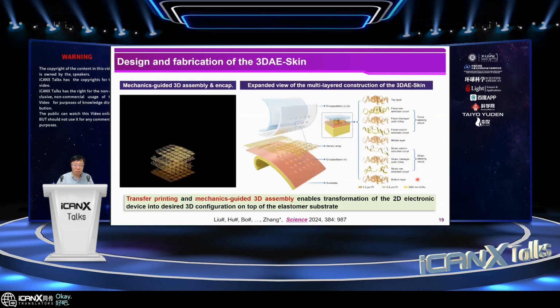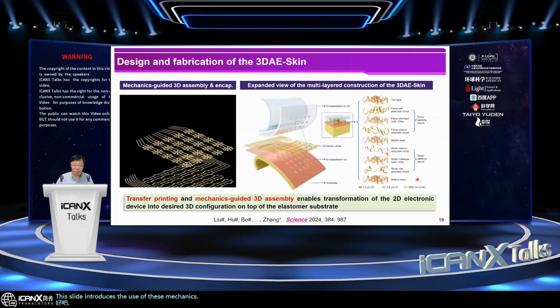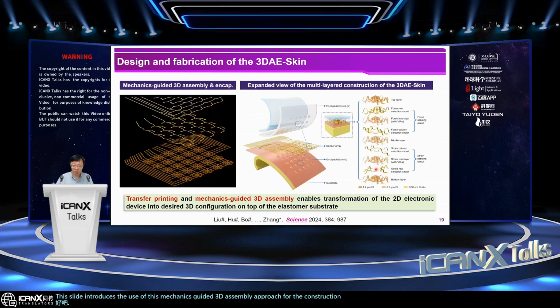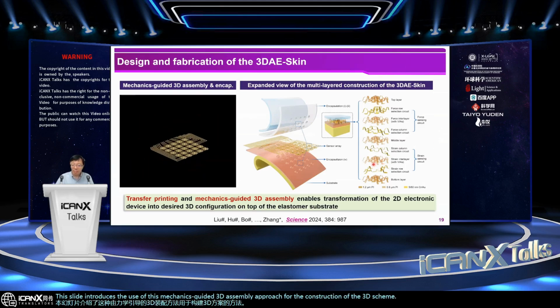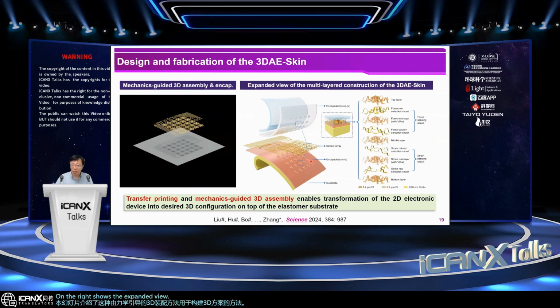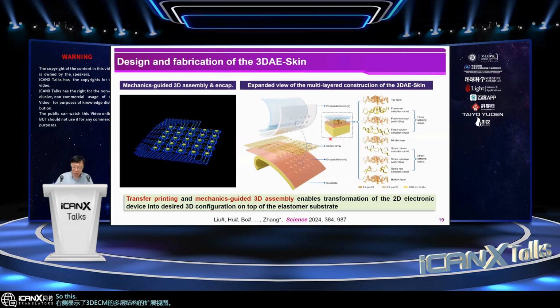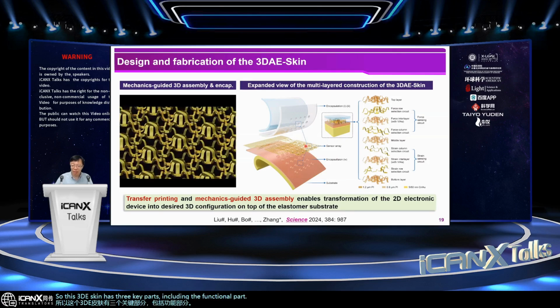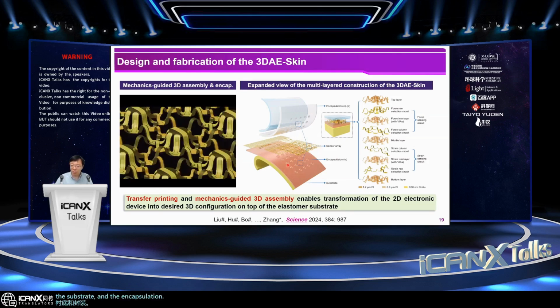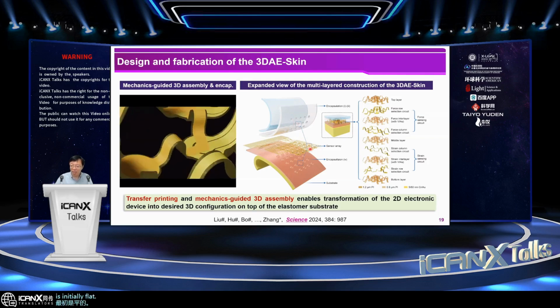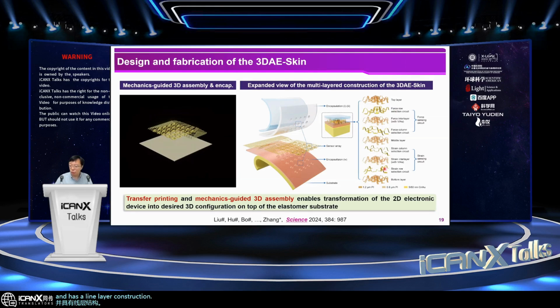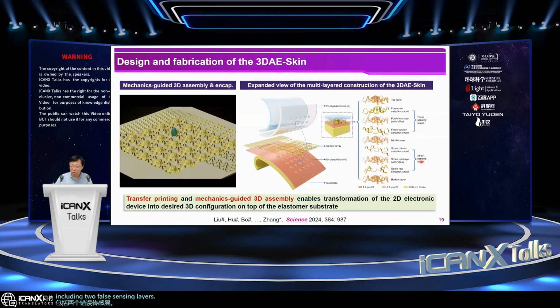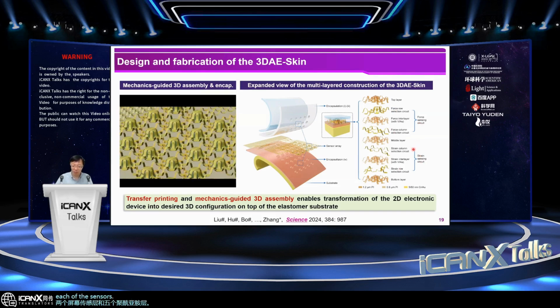Okay, this slide introduces the use of this mechanics guided 3D assembly approach for the construction of the 3D e-skin. On the right shows the expanded view of the multi-layered construction of the 3D e-skin. So this 3D e-skin has three key parts, including the functional part, the substrate, and the encapsulation. And the functional part is initially flat and has a nine layer construction, including 2 force sensing layers, 2 strain sensing layers, and 5 polyimide layers that encase each of the sensing layers.